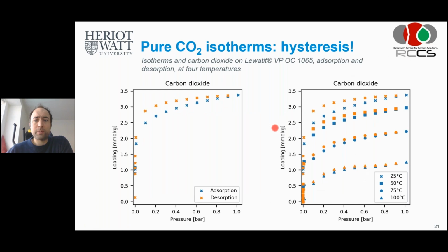Now, other interesting observations. Yeah, this is what I just said before. This is again for Lewatit. You see that if we go to higher temperatures for Lewatit, the hysteresis becomes much smaller. So that would support a kinetic effect, and then either what I said before, it might be mass transfer related, so channels closing, or it might be chemical kinetics related, so that you simply have an energy hump that you need to overcome for the desorption.